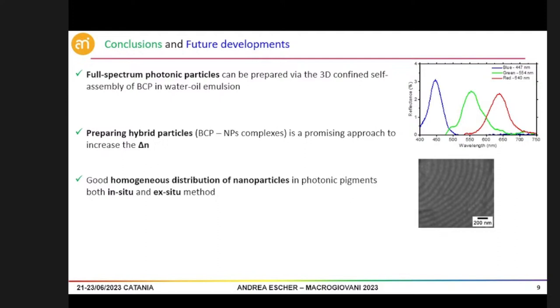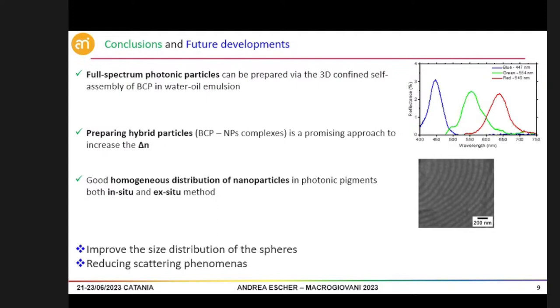We have prepared hybrid particles that are a very promising approach to increase the delta n of these photonic pigments. And finally, we also obtained a very good distribution of the nanoparticles inside one of the two polymer domains. For future development, we want to improve the size distribution of the spheres and also reduce scattering phenomena of these pigments.